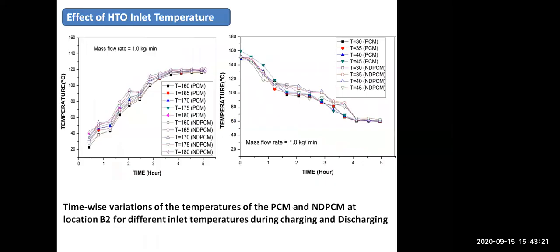The effect of heat transfer fluid inlet temperature. The melting time was decreased by 19% for pure PCM and about 21% for NDPCM when the inlet temperature was increased from 160 to 180 degrees Celsius. The solidification time was reduced by 10% for PCM and 14% for NDPCM when the heat transfer fluid inlet temperature was decreased from 45 to 30 degrees Celsius.